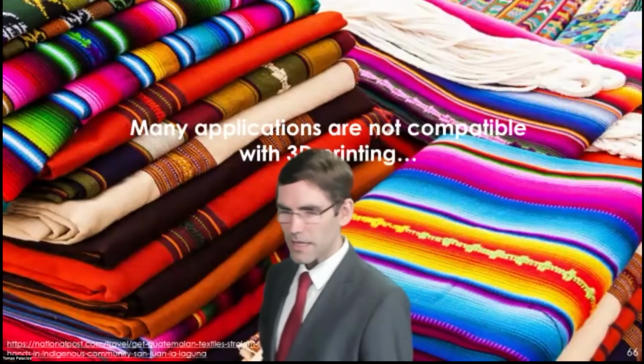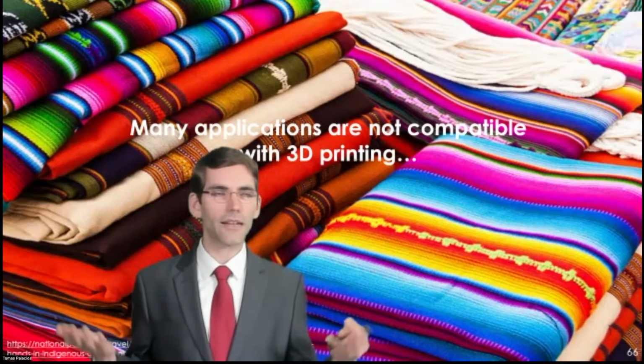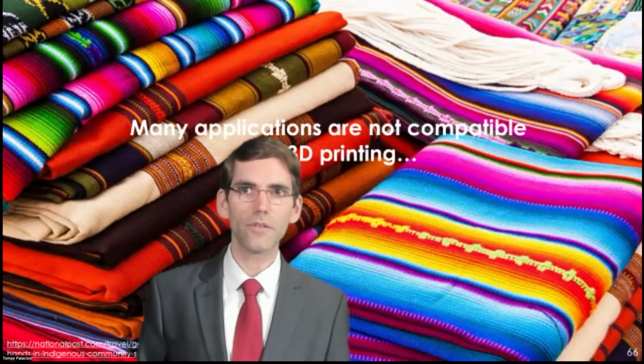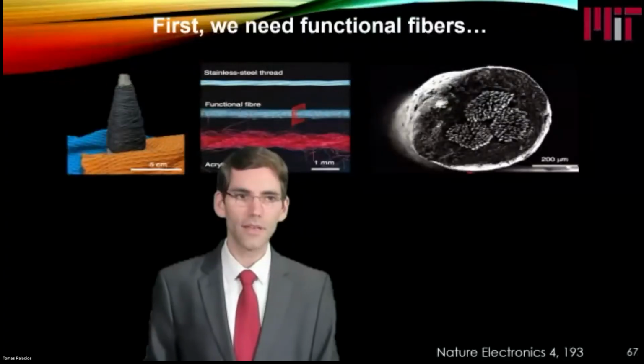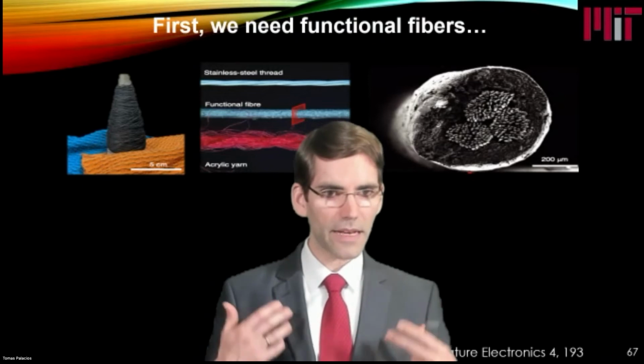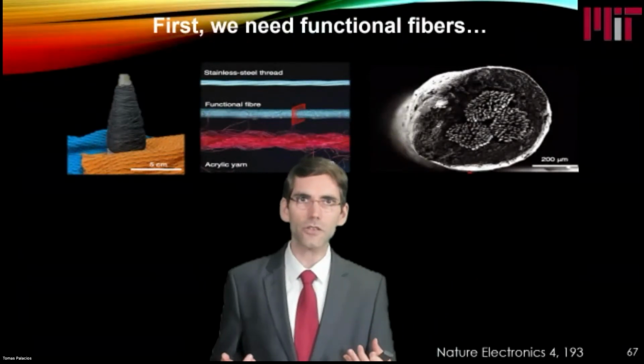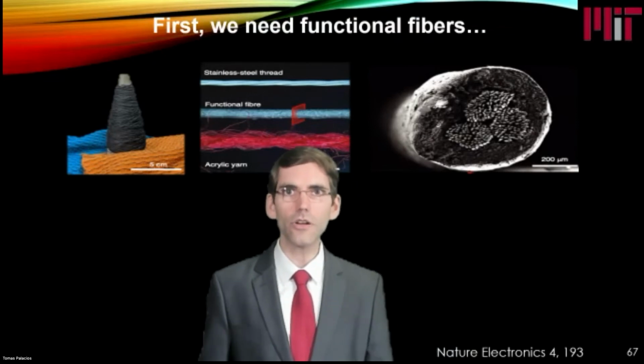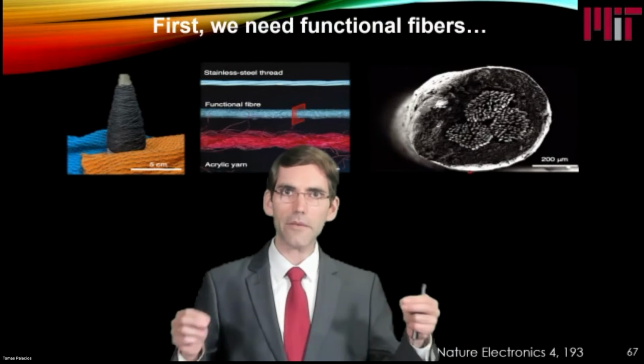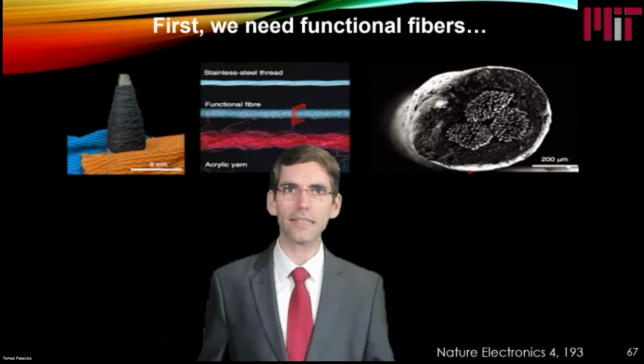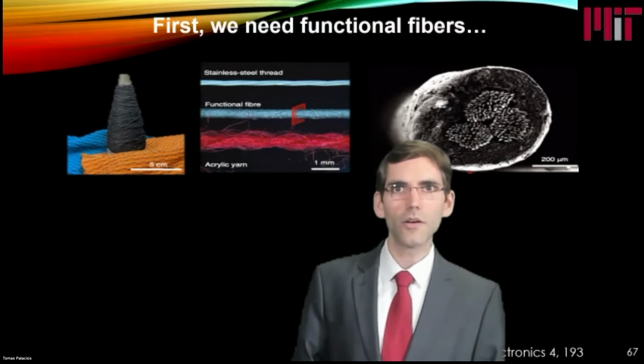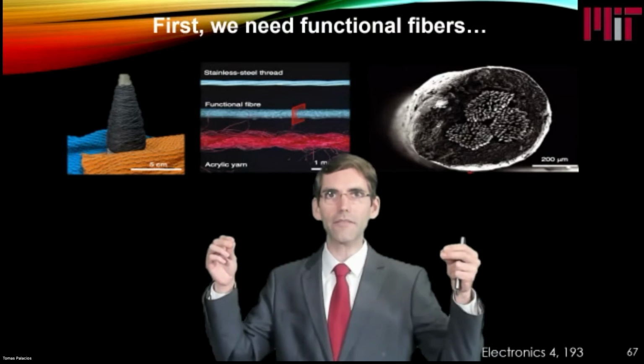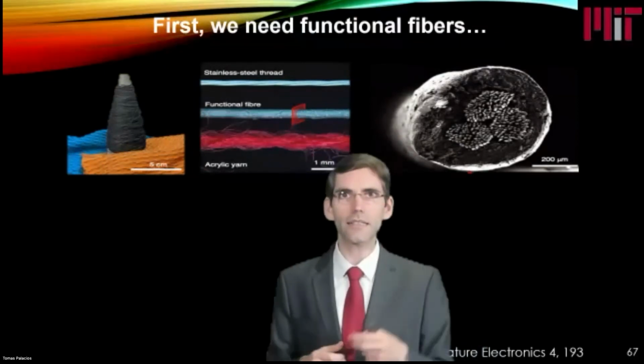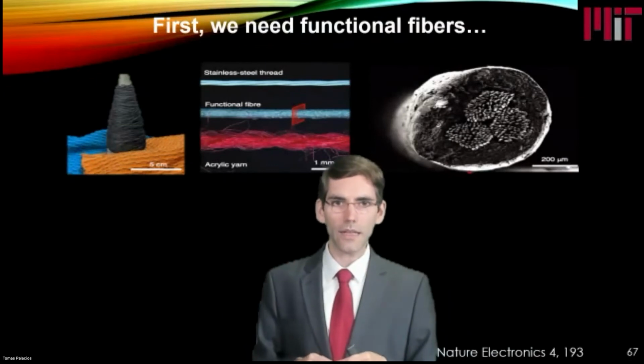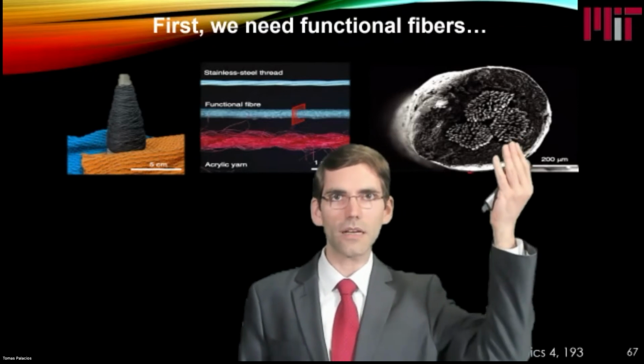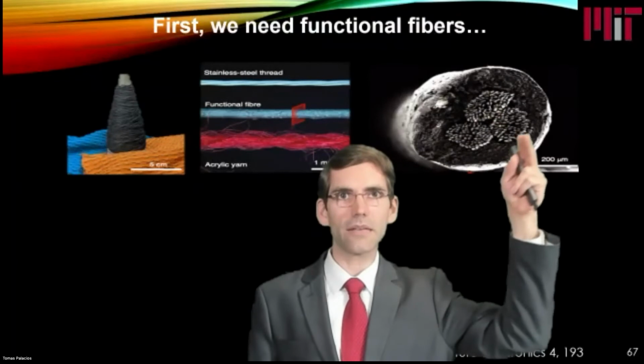But even though 3D printing is very interesting, there are many other applications that are not compatible with 3D printing. For example, textiles and fabrics. So we believe that there is a very interesting opportunity if we are able to bring sensors and semiconductor chips and semiconductor-based electronics to the fibers that make up our fabrics and textiles. And this is just a simple example of that. We took a metallic fiber, a metallic stainless steel thread, and we coated it with a graphitic material shown here. So this is the metallic fibers with the graphitic material.